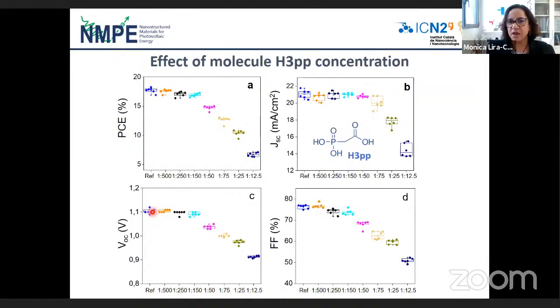In this case, we were thinking about it, we don't see any effect from the additive here because we are diluting too much, or we are not passivating deep defects. Because if we passivate deep defects, non-radiative recombination decreases and the efficiency and voltage should increase. So we are not doing that. That's the first thing these results told us.